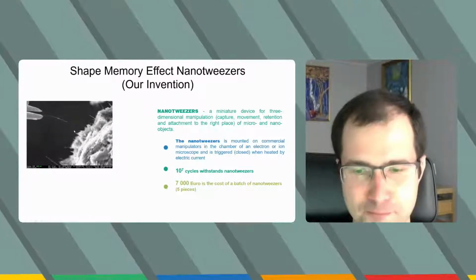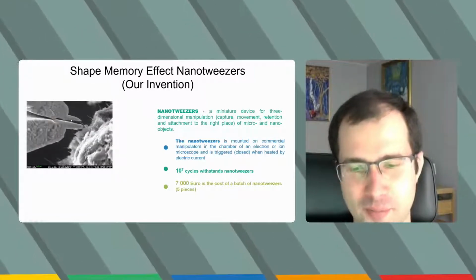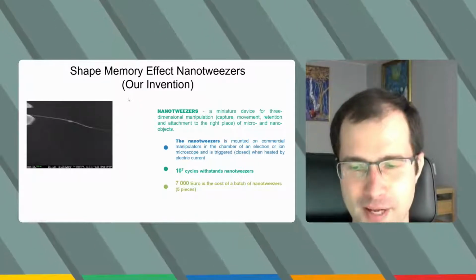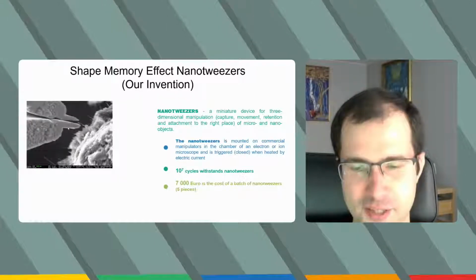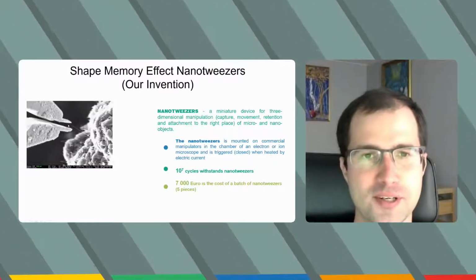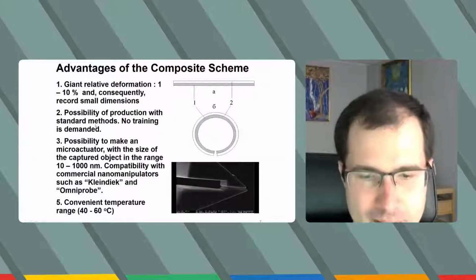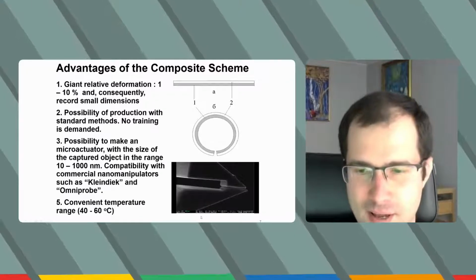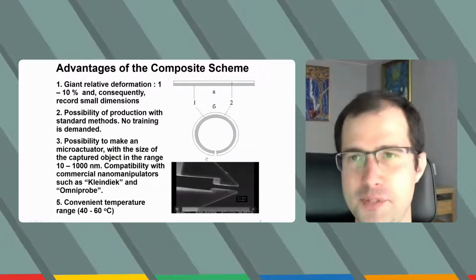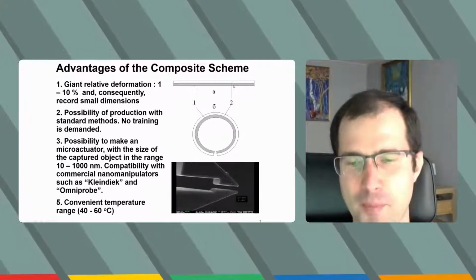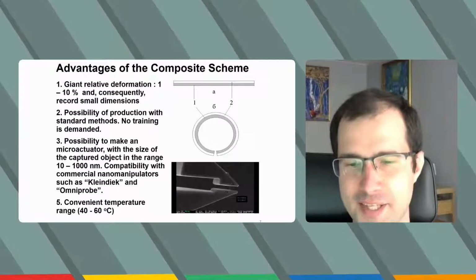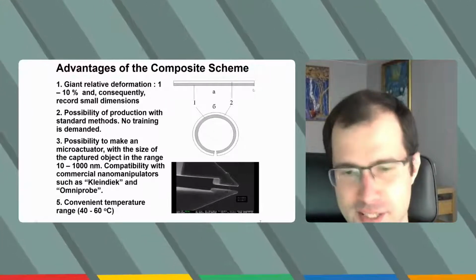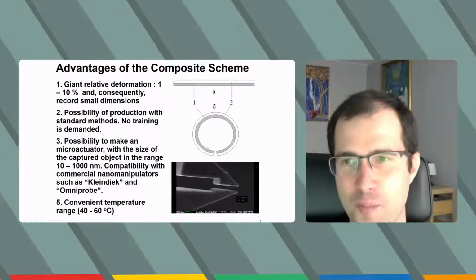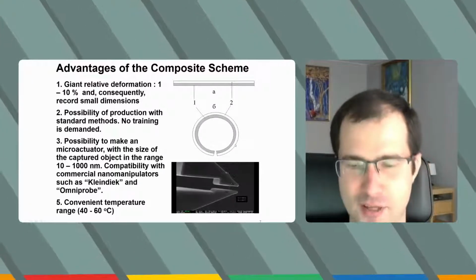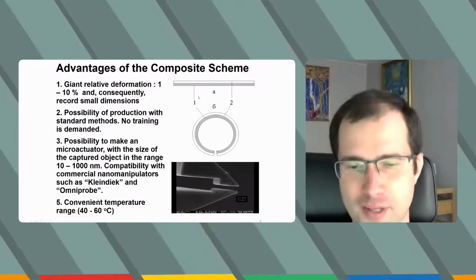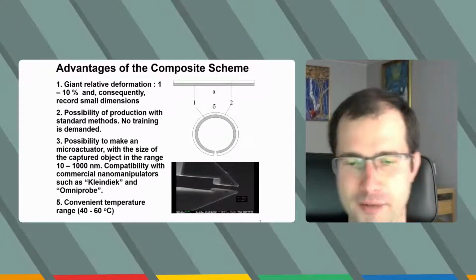At this slide, you can see nanotweezers made from composite bimetal material, titanium 2 nickel copper with shape memory effect, and another layer that is an elastic layer. It is triggered while heating the material. Here you can see carbon nanotubes being grabbed. The key here is composite functional materials. The bimetal material is a pseudoplastically stretched shape memory effect ribbon of titanium 2 nickel copper, stretched by 1% at the martensitic cold state, and the second is an elastic layer. What is bending? Bending is compression on the inner side and stretching on the outer side. So we obtain a material with reversible shape memory effect, because shape memory effect itself is only one way.